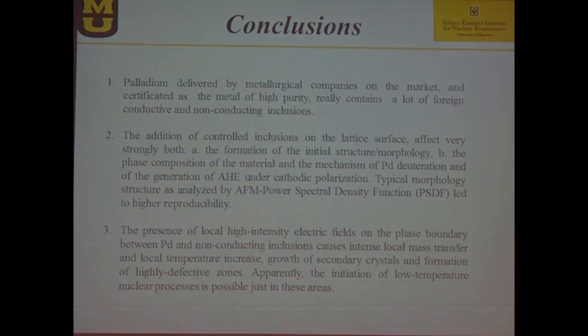You remember the carbon, the black spots, the carbon spots, which are generating electric field, but not only these, some other materials are doing the same thing, and creating high electric fields between the non-conductive and the conductive phases on the surface of the matrix, and those are highly important. And if nuclear or any other reaction takes place, it must be on these sites.